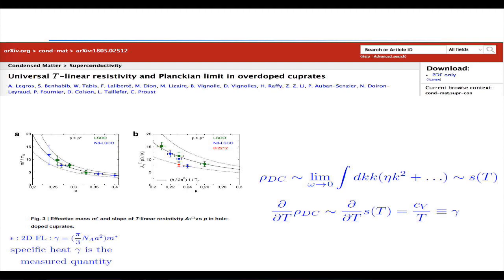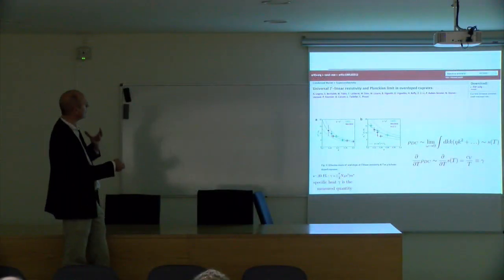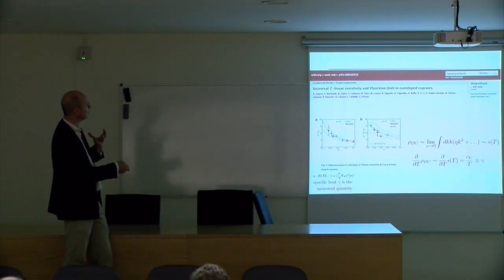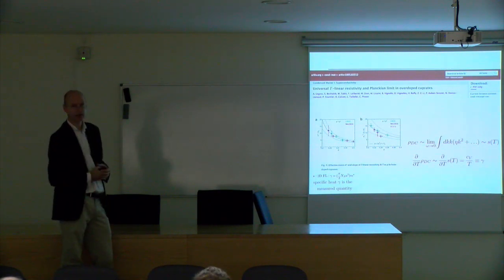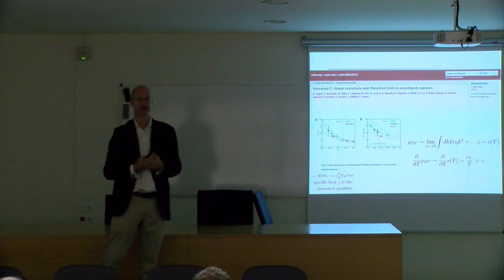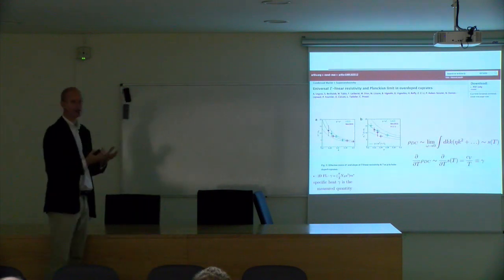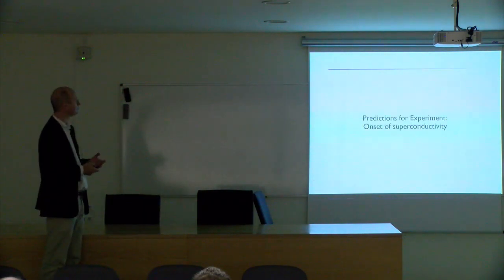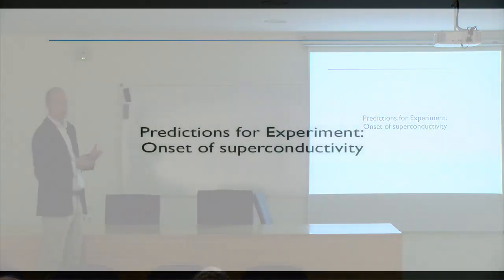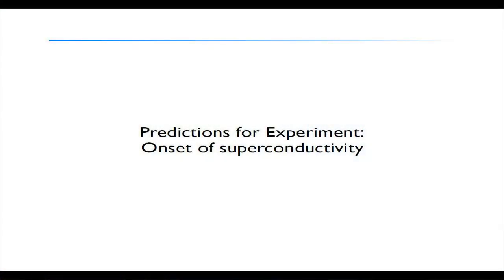And even though, as you see from the data, it's very scattery, the error bars are very large, here they show that the specific heat, indeed as a function of doping, also goes down, just like the resistivity. So at least qualitatively here, there is again a scenario that fits this larger picture.